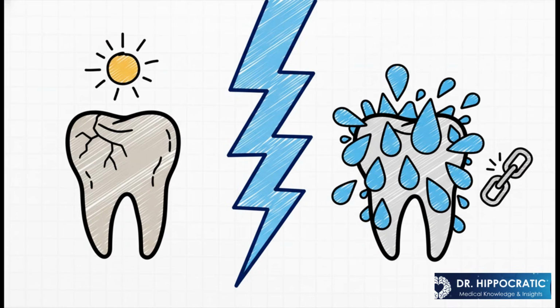You see, GICs need a very specific environment to work. If you get that perfect bone-dry isolation with something like a rubber dam, you actually risk desiccating or totally drying out the tooth and the cement, which, believe it or not, weakens it. But on the flip side, if you let even a little bit of saliva contaminate the prep, the proteins in it form this slick film, a salivary pellicle, that completely blocks the chemical bond. It really is a clinical tightrope.